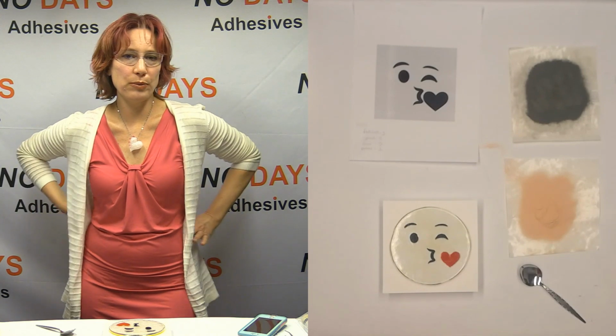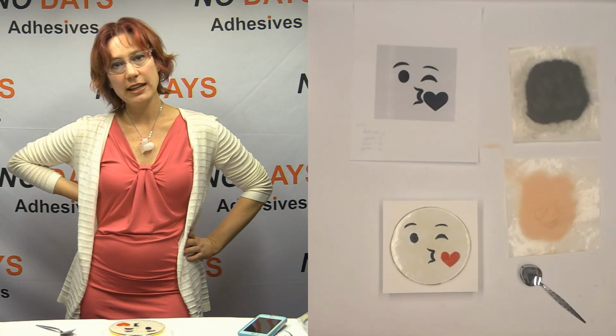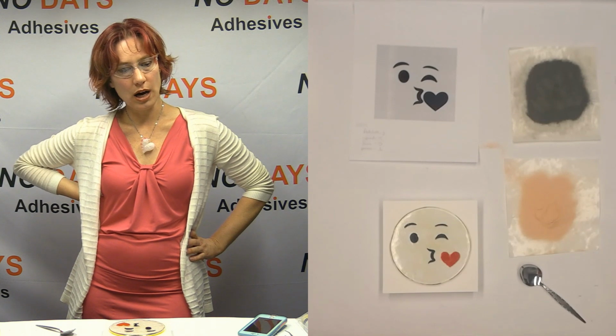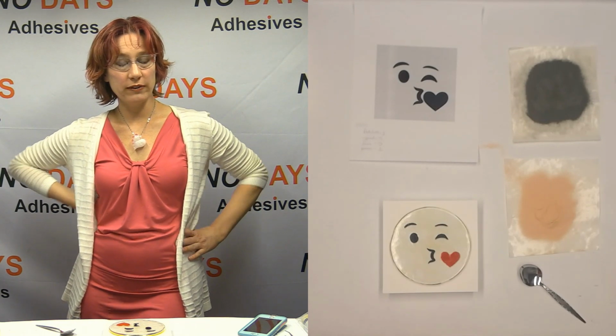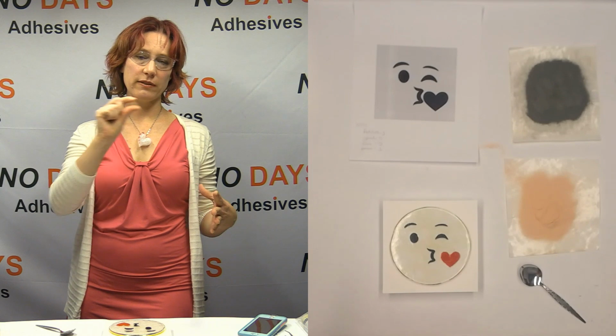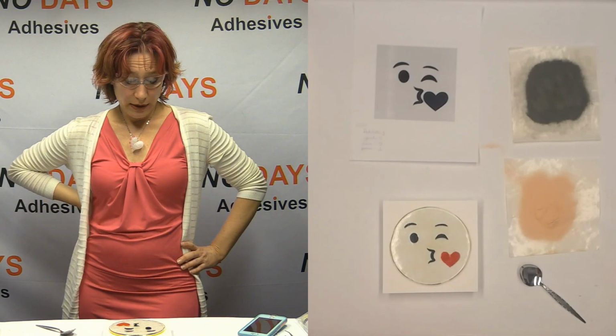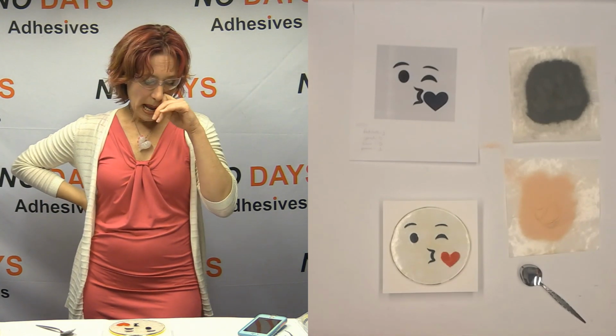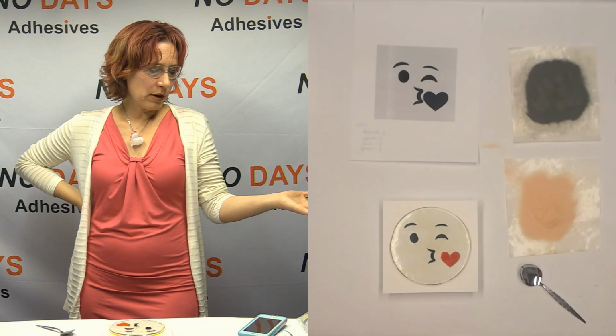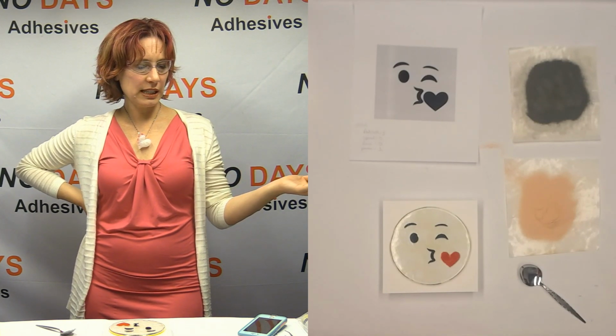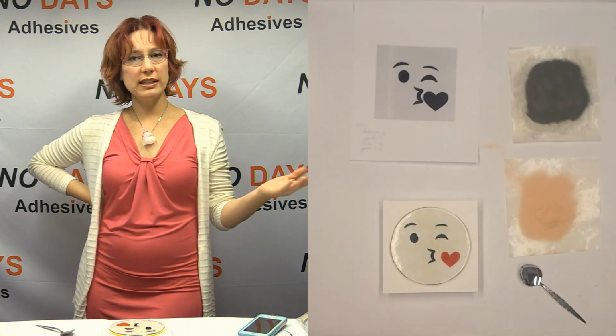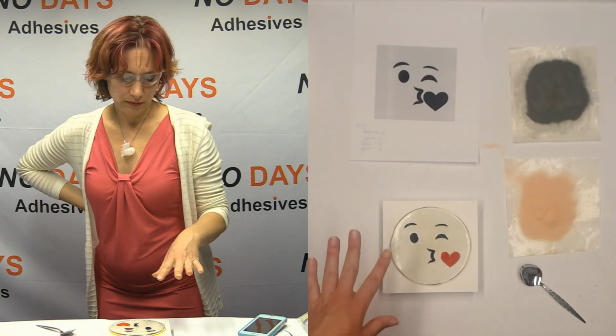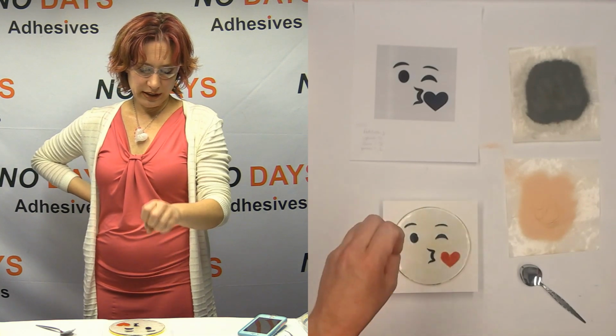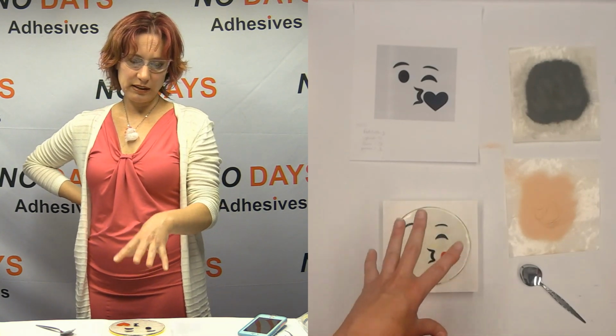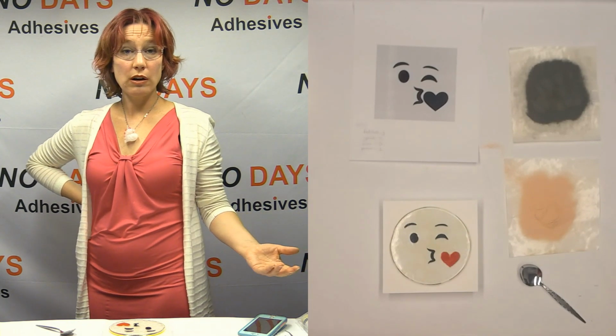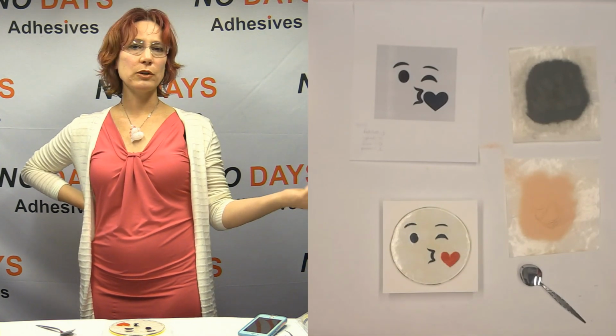I've had a shelf break, and it's unfortunate, but I did learn my lesson, and thankfully I had a backup shelf, so hurrah. I can still use the cracked shelf, and if I want to fire bigger pieces on it, I just put 1/8 of an inch fiber paper all the way across the top. Anyway, this is a full fuse. I'll probably go 300 degrees an hour up to 1,000 and hold it for 45 minutes, and then I typically do a bubble squeeze even though I've got all the powders and everything, right? So I've got this bubble squeeze segment, which is 50 degrees an hour up to 1250. And I hold that for about 20 minutes.